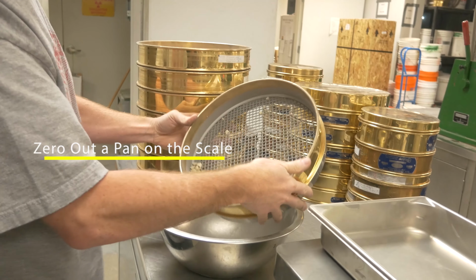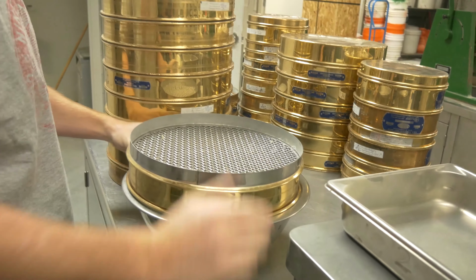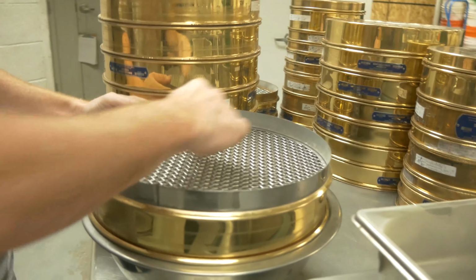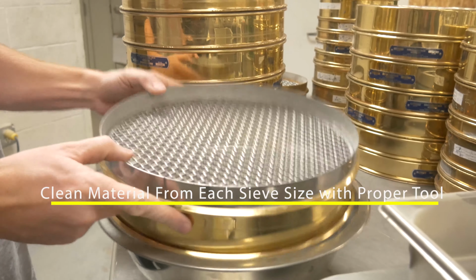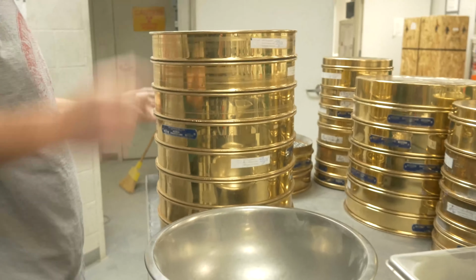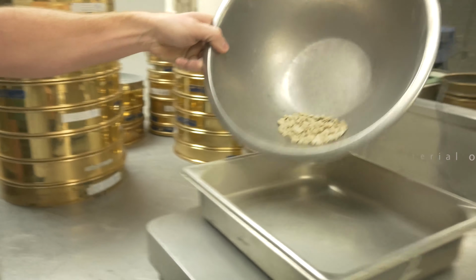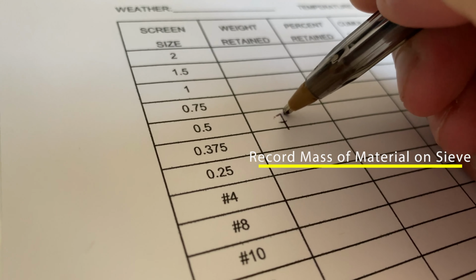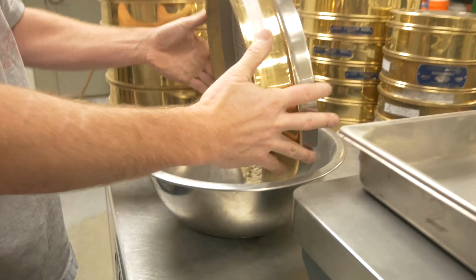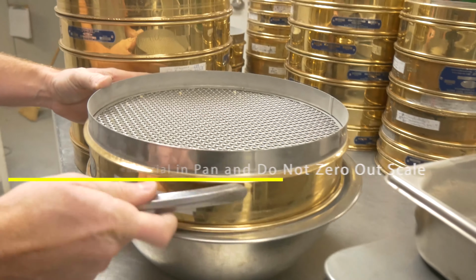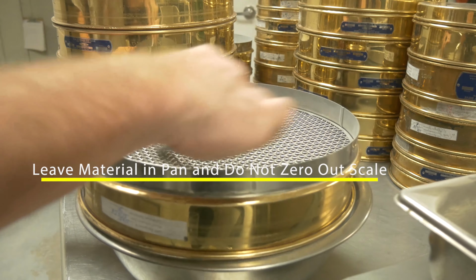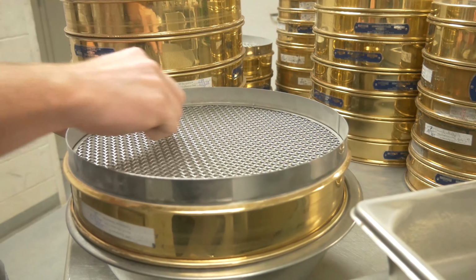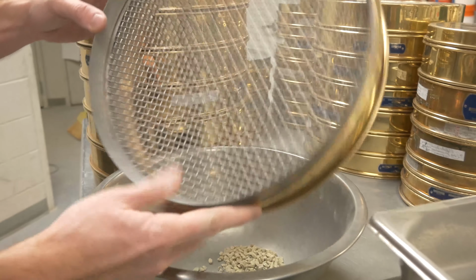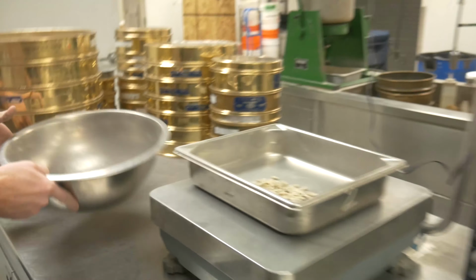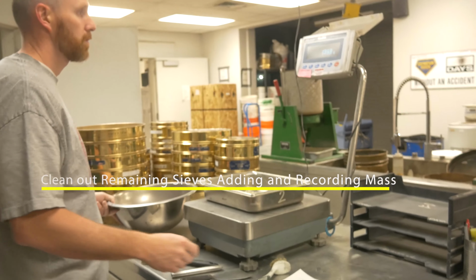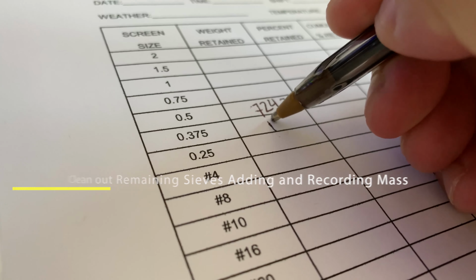Zero out a pan on the scale. Clean all the material from the sieve with your proper tool. Record the mass of the material on the sieve. Leave the material in the pan and do not zero out the scale. Clean out the remaining sieves, adding and recording the mass one after another.